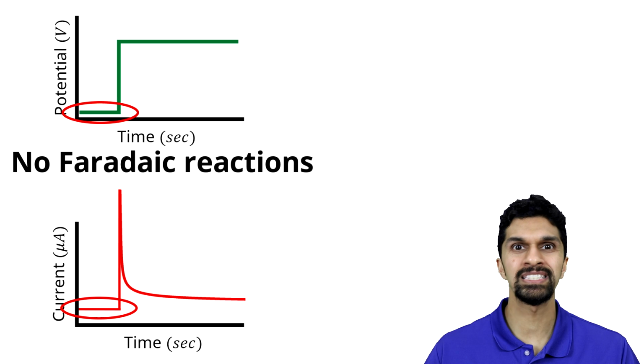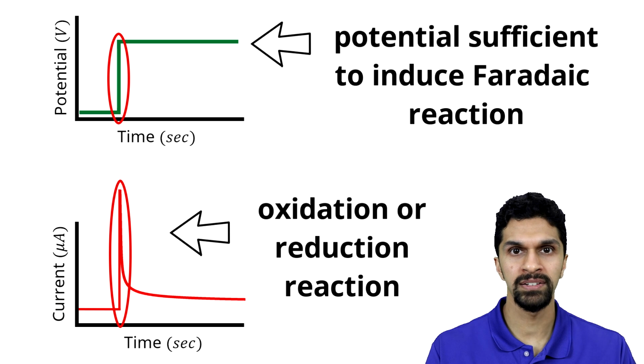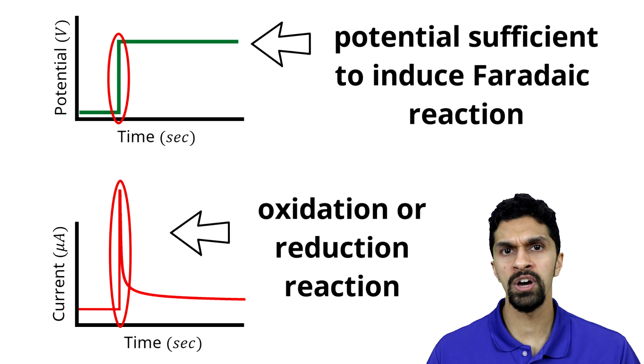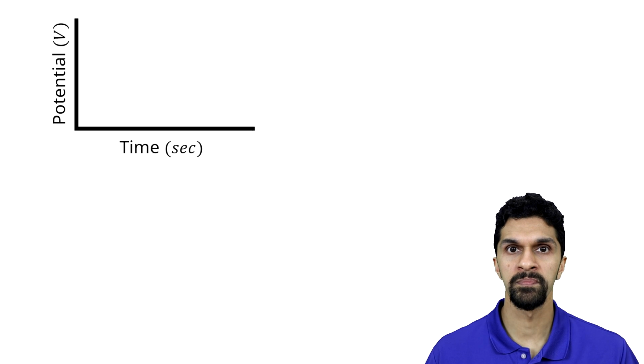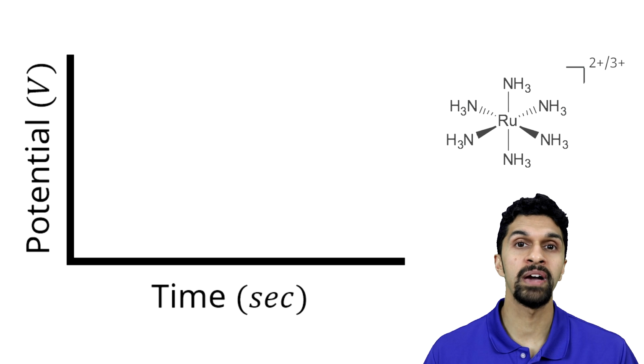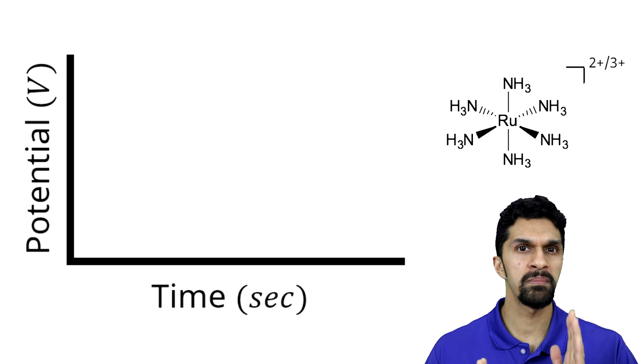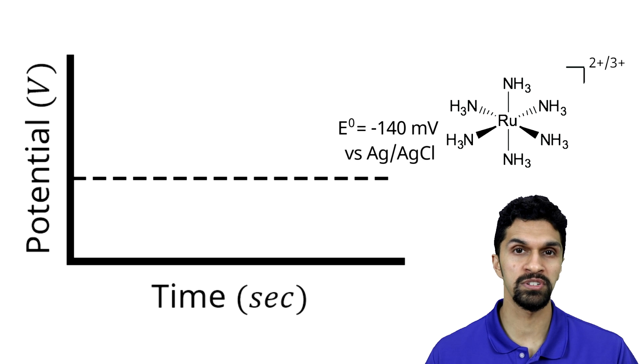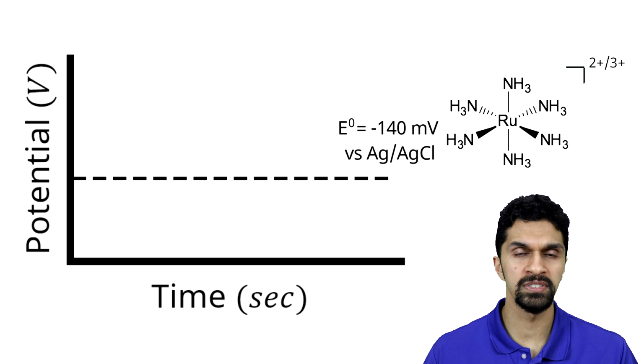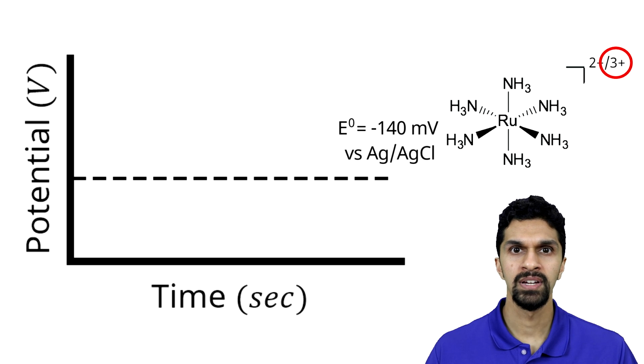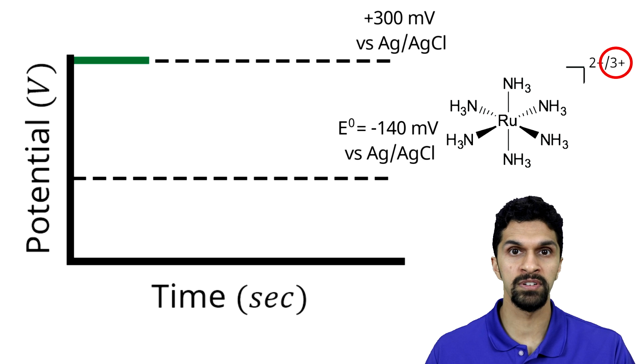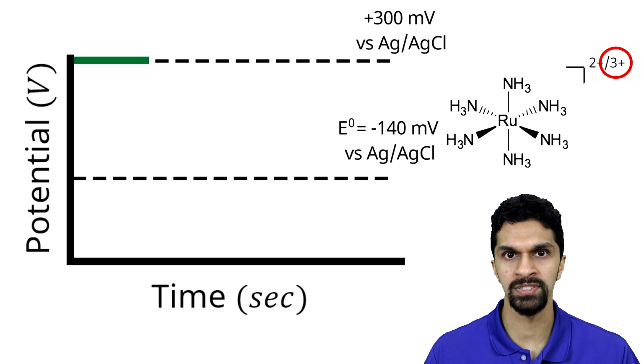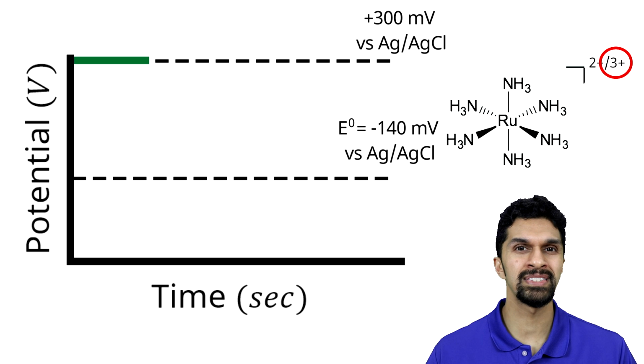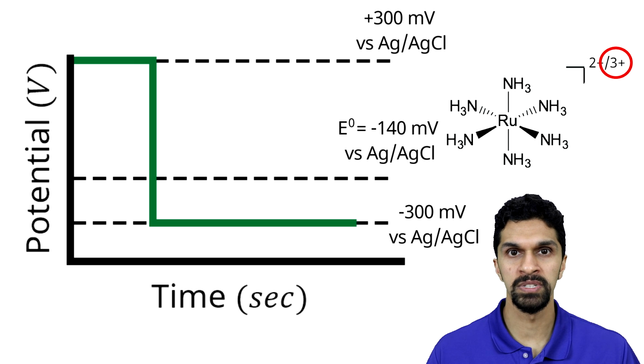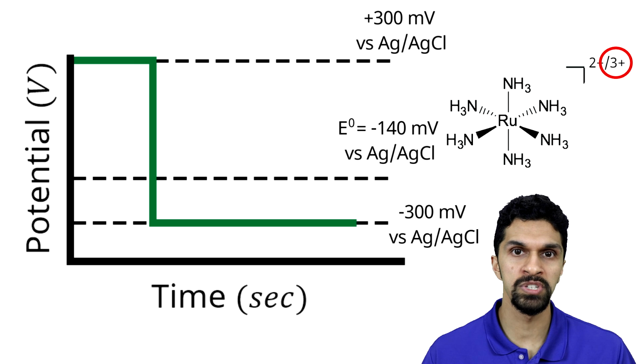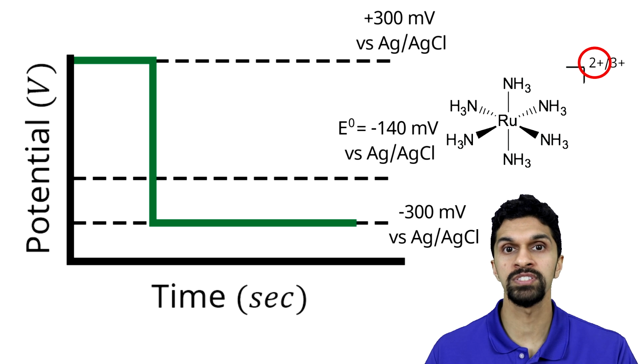When the experiment starts, we then step the potential to a point that is either sufficiently high to induce an oxidation reaction or sufficiently low to induce a reduction reaction. For example, the standard redox potential for the ruthenium hexamine 2+/3+ redox pair is about -140 millivolts versus silver-silver chloride. If my starting material is ruthenium hexamine in the 3+ oxidation state, I might start the potential at +300 millivolts, keeping ruthenium hexamine in that 3+ oxidation state. When the experiment starts, I would then step the potential to, say, -300 millivolts, sufficiently negative to reduce ruthenium hexamine from the 3+ to the 2+ oxidation state.